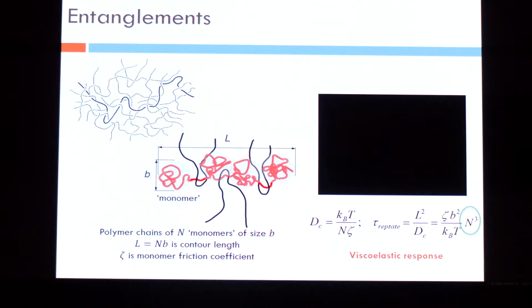And this is the reason why in one of the earlier videos you could see that I can take a liquid and I can cut it almost like a solid. Because the cutting motion is so fast that the polymer is not able to relax back, and therefore it behaves like a solid and I can cut it. I can't really cut a liquid. The typical liquids that we encounter in daily life, you can't cut a jet of water falling out of a tap, right? But here, a jet of polymer that is coming out of a tap, you can cut it because the cutting time is much smaller than the relaxation time of the polymer.